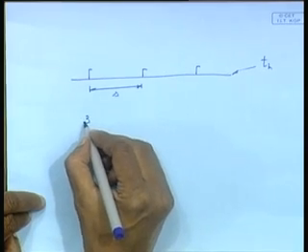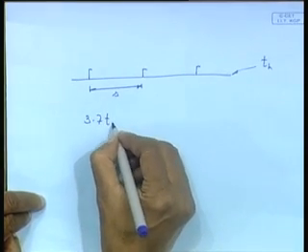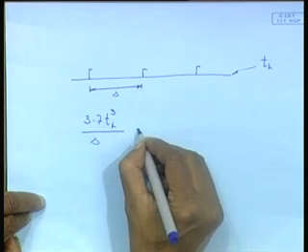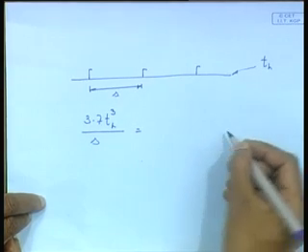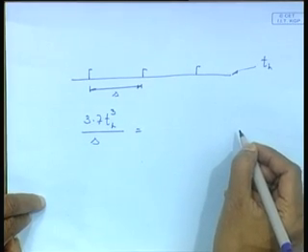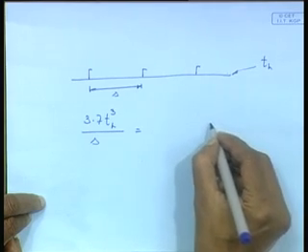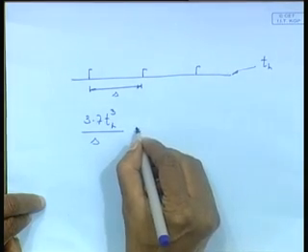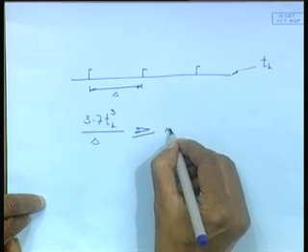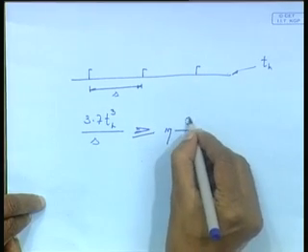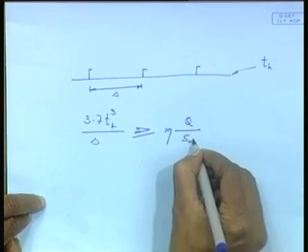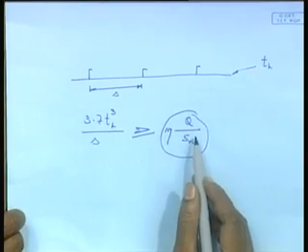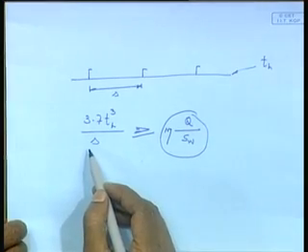So, what I calculate is 3.7 TH cube divided by delta, whatever value it is giving, right. I should be finalizing the weld parameters in such a way that it remains less than this figure.